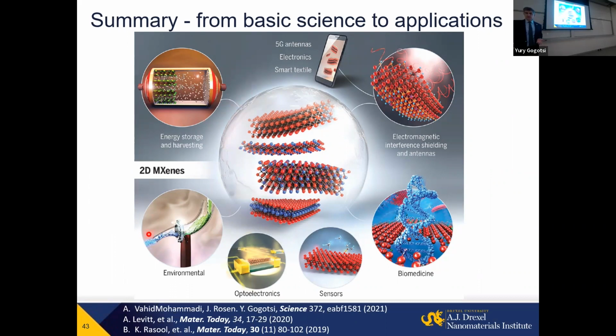because beyond energy storage or optoelectronics, there are very important potential environmental applications, separating hydrogen, for example, from methane, or water desalination, deionization, filtration, purification. And again, by applying potential, you can do things that other materials cannot do because, say, with polymer or with oxide clay filters, you can do filtration, but you cannot control it electrochemically. With graphene oxide, you can do the same. A very nice membrane was shown by the Manchester group, for example. But when you make graphene, it's hydrophobic. MXene is hydrophilic and electrically conducting. So you can again run current, apply potential, and control rejection, for example, of certain ions or molecules here.